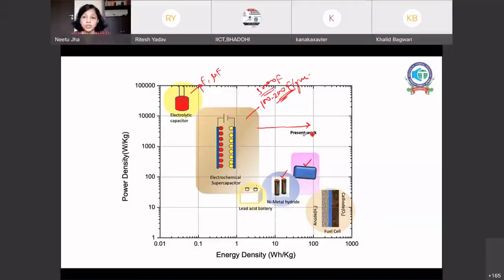because in supercapacitors you do not use any lithium or these metallic systems. You can use metal oxide or some polymers to increase the charge efficiency, but then the choice is in your hand. We are trying to increase the performance of supercapacitors using different electrolytes which are more stable for large potential windows, and we are trying to increase the energy density of these supercapacitors.